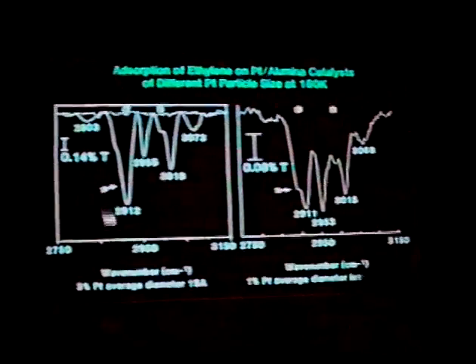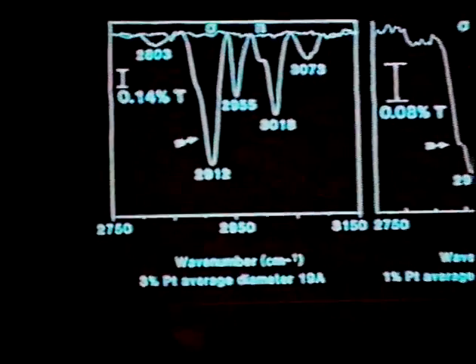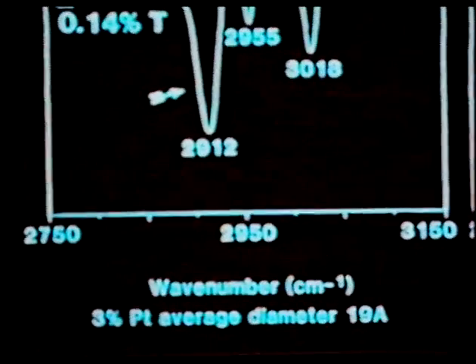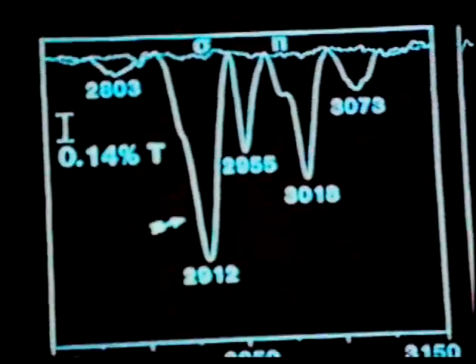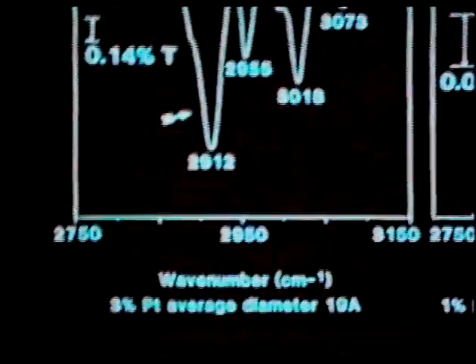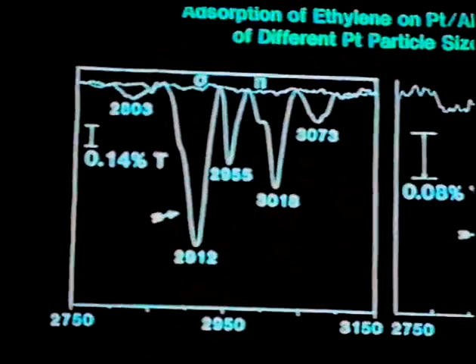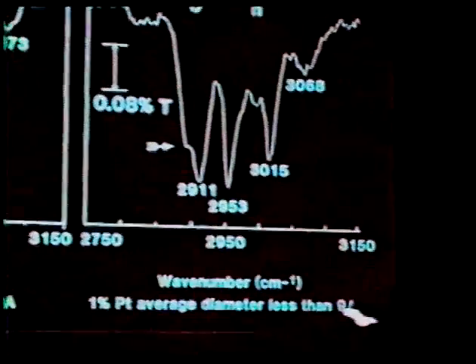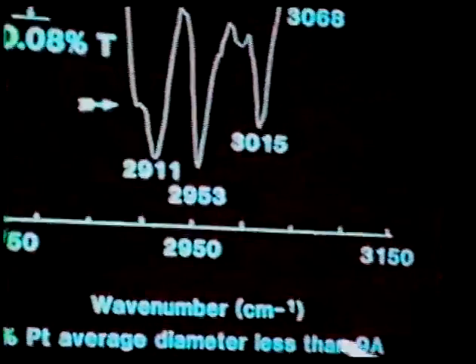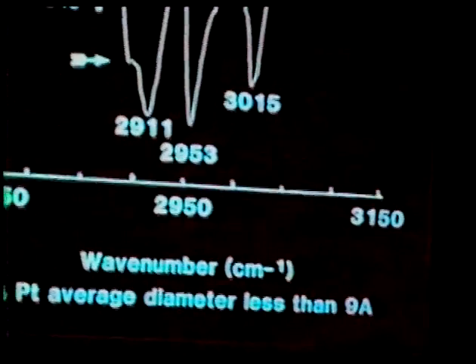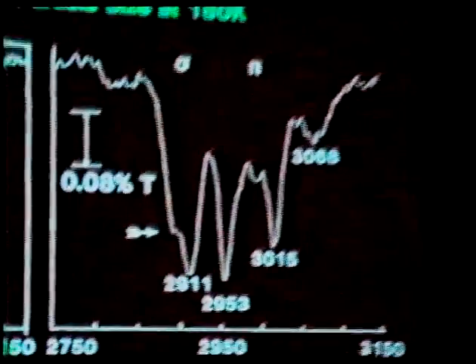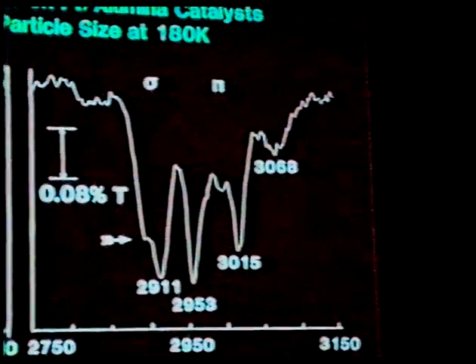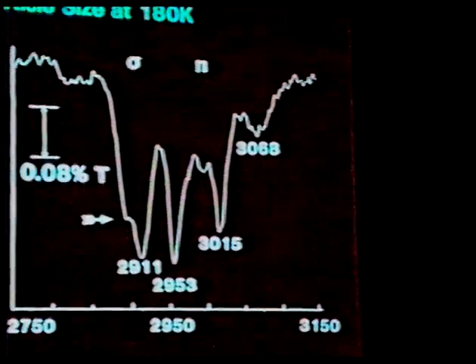And if you do that, you do indeed see a change in the relative contributions of the di-sigma-bonded and the pi-bonded species. What we have here is a catalyst containing 3 weight % platinum. Average diameter is about 19 angstroms, and I assure you we've done almost everything we can to make sure that indeed that's the size of these particles. In the same sense, what we have here is a 1% platinum catalyst. These particles are less than 9 angstroms, is what we believe. They exhibit unit dispersion by any kind of dispersion measurement that you would want to make. Direct observation with TEM, we were unable to observe any particles whatsoever.